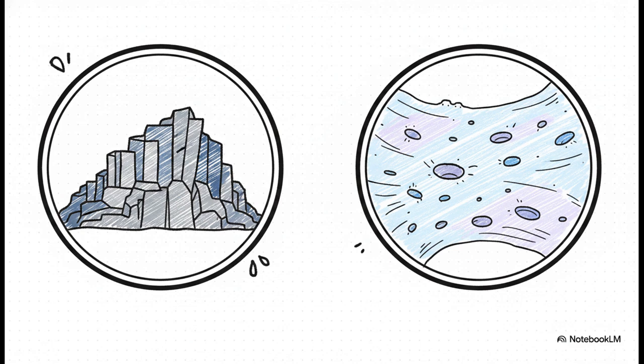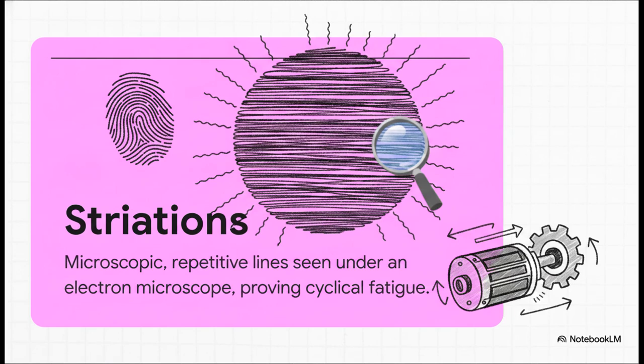But in the final, sudden fracture zone of our fatigue case, you'll usually see dimples. These are tiny, hollowed-out little craters that show us ductile tearing, which basically means the metal stretched out at a microscopic level right before that final snap. But hold on, dimples only tell us about that final sudden break. What about the slow, silent killing phase? Well, that's where we find our smoking gun.